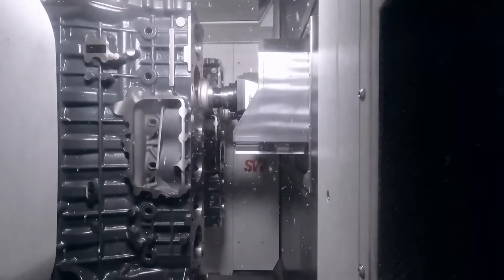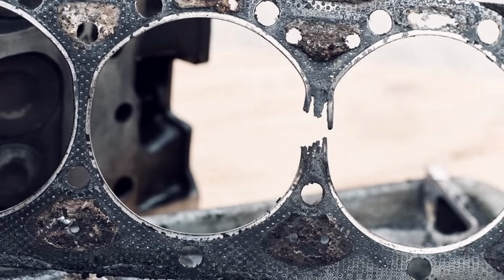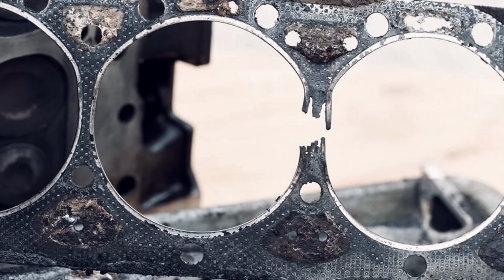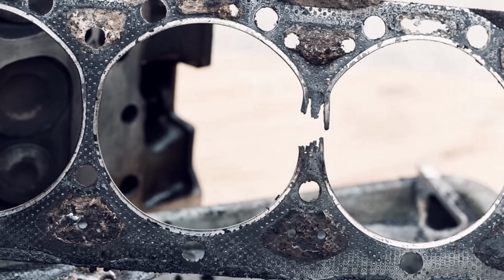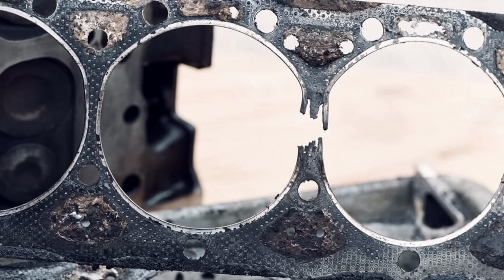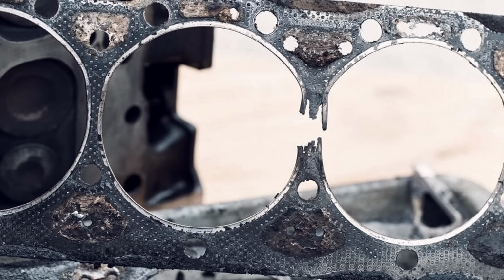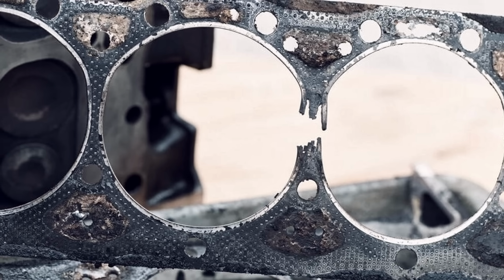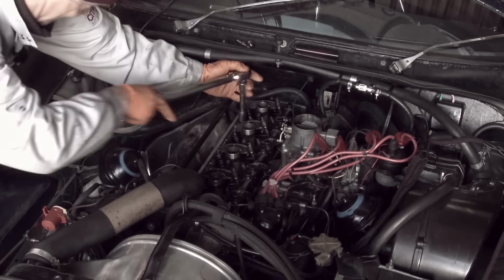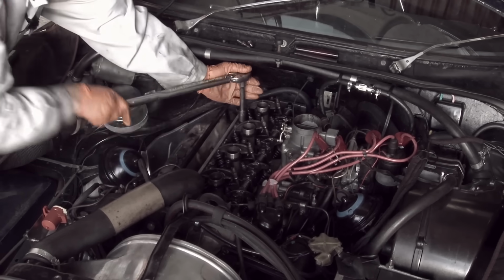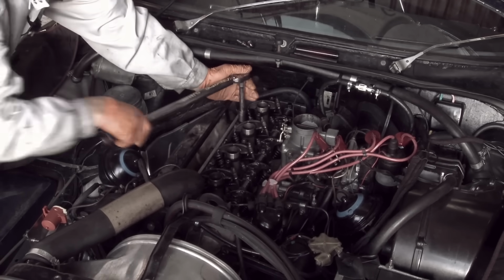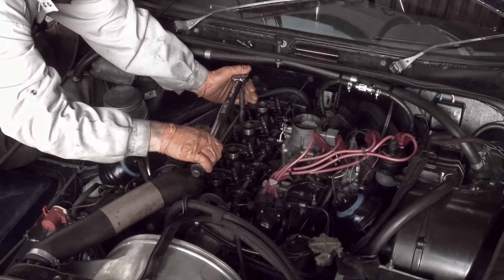Because of its reliance on its surface coating for sealing, composite gaskets are easily compromised by being pressed into dirt or foreign objects. They also rapidly degrade when exposed to abnormal engine conditions, with the two most common modes of failure being composite swell from the steam of overheating and combustion seal failure from both overheating and detonation. Much like copper clad gaskets, the compressibility of a composite head gasket is carefully matched to its application and the clamping force of the head bolts.